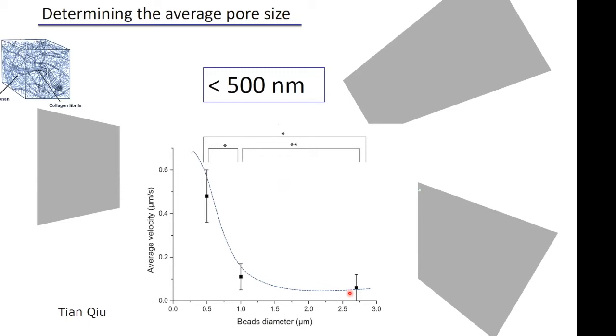We have looked at many other systems, and it always turns out that you have to be on the sub-micron scale. So there's a real purpose here for going in the direction of nano systems and nanorobotic systems. And here you see the motion velocity of these particles as a function of their size, and they don't really want to move because they get stuck. And then below these sort of 500 nanometers, they start to slip through. And hence, if you make things small enough, you will be able to penetrate tissue more easily, i.e. you can use weaker fields, which are much more easily implemented in a real medical setting.